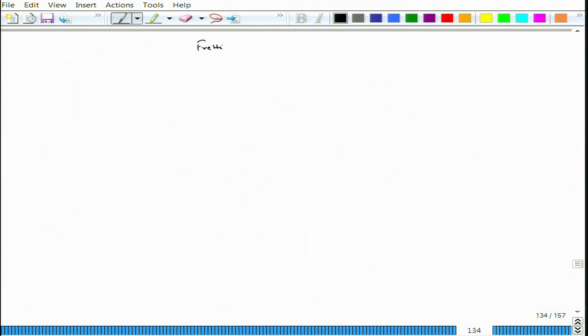Now let us look at another form of erosion corrosion: fretting corrosion. Fretting happens when two meeting surfaces are tightly fitted and there is a very small amplitude of vibration — even a few microns — which leads to a fretting action between the interfaces. If corrosive conditions are also present, this can lead to corrosion of the material.